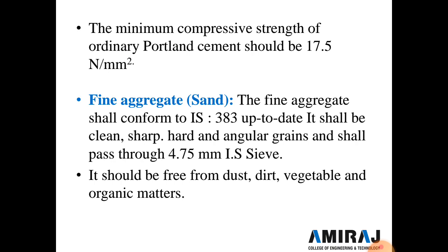We also use fine aggregate to prepare concrete. The fine aggregate shall conform to IS 383 up to date, and it shall be clean, sharp, hard and angular grains, and shall pass through the 4.75 mm IS sieve. It should be free from dust, dirt, vegetable and organic matter, and sea sand shall not generally be used. In the construction industry we generally use only river or pit sand. Sea sand cannot be used due to the salty material inside the sand.